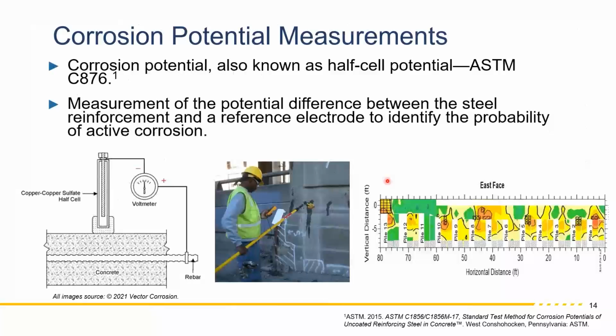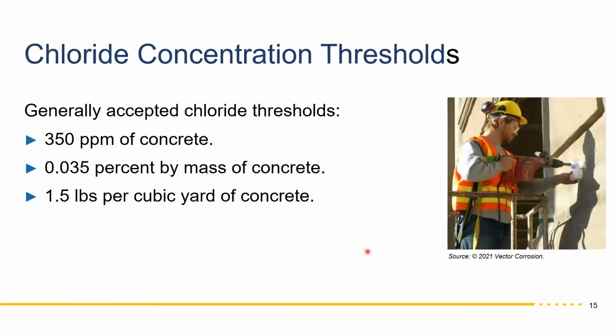Another test that's often done is called half cell potential. Okay, it's coming up. The half cell potential testing. So you basically core into the concrete, into the rebar. You connect that. It's kind of like a voltmeter, and you measure the difference in potential from the surface to the rebar, and then you map it out here. Whatever low values you have indicate areas of high probability of corrosion. So that's an ASTM standard, a very simple but effective test that's done here.